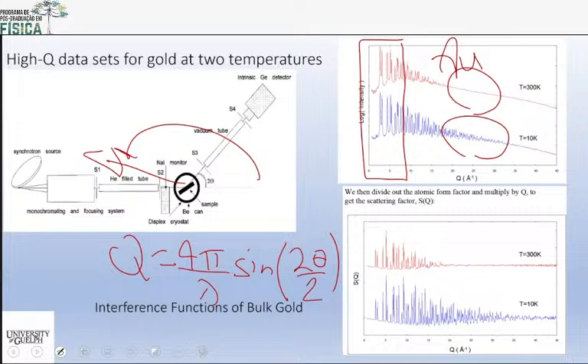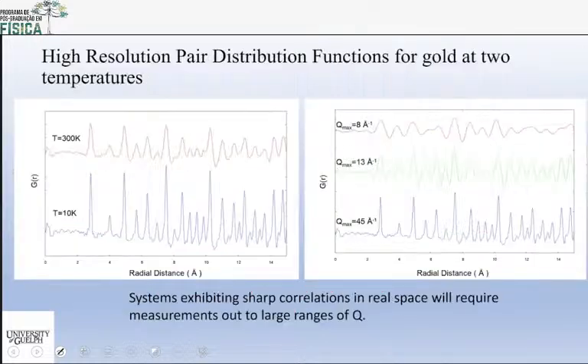Because what we're going to do is measure a diffraction pattern all the way out to very high Q. And notice that the units of Q are inverse angstroms. So the neat thing is if you take a Fourier transform of that pattern, there's a little bit of processing you need, and you Fourier transform that, you get a graph that is now in angstroms, and this is what you get. So what happens here on the left is you have a pattern that looks like a diffraction pattern. And this is where you remember that, like, I think it was Ashcroft and Mermin or Kittel or any solid-state textbook tells you that the Fourier transform of a face-centered cubic lattice is a body-centered cubic lattice. And this is exactly what this is. This is the Fourier transform of that scattering pattern, okay?